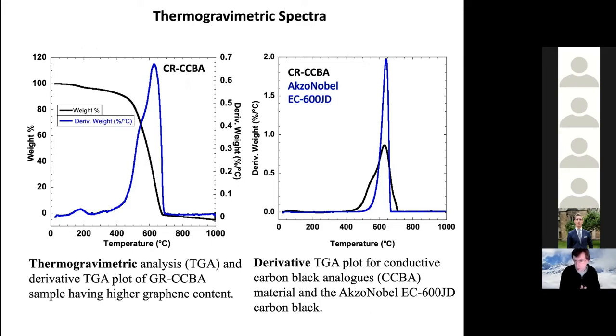One method we have used to assess the relative phase fractions, the relative contents in the product of the two forms of sp2 carbon, has actually been TGA. What you're seeing on the left is a thermogravimetric spectrum, the black line, and the blue being the derivative of that. You can see that there's certainly a shoulder on the left. In fact, this TGA does suggest that there are two different forms of carbon with different thermal oxidative reactivities. And those two different forms correspond to the lower peak, the nanographene, versus the higher temperature peak corresponding to the graphitic carbon black analog. How do we know that? Well, we've done comparative TGA and/or derivative peak matching using different reference materials.